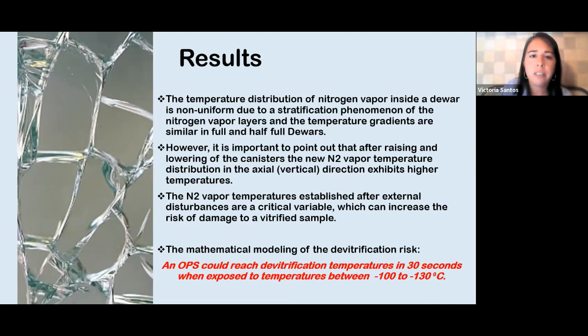So the results tell us there is a temperature distribution of nitrogen vapor inside a dewar that is non-uniform, and it's because we have a stratification phenomenon of these nitrogen vapor layers. These temperature gradients are similar in a full and half-full dewar. However, when we disturb the nitrogen vapor, we establish a new axial distribution of temperatures, and we have higher temperatures overall. The nitrogen vapor temperature established after this disturbance is a critical value because we increase the risk of damage to vitrified samples. The mathematical modeling tells us that an OPS could reach a devitrification temperature in about 30 seconds when exposed to -100 to -130 degrees Celsius.